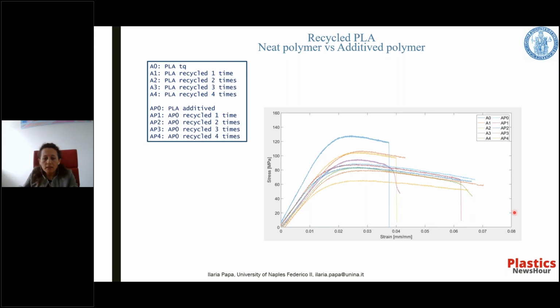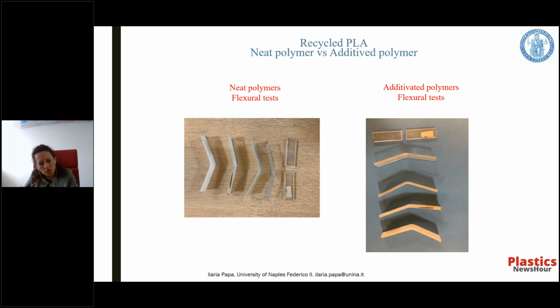And of course, depending on the line, we can see that the modulus and the mechanical features decrease as the number of the recycle operations increases, and this happens for both neat and additive PLA. I have also shown you these samples to show the change of the breakage, the failure breakage of the flexural test after five cycles of recycling,